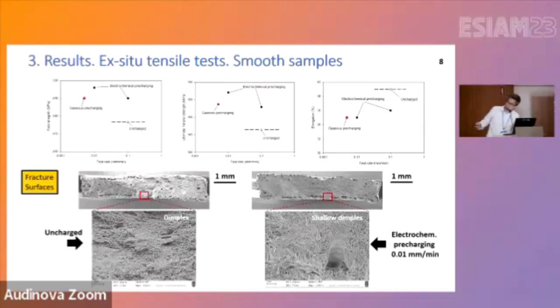Regarding the fracture surfaces, dimples indicating ductile fracture were observed in the uncharged specimens without hydrogen. However, in the case of the samples precharged electrochemically, which corresponds to this strain rate, this point, we have observed shallow dimples, which could be associated with hydrogen-enhanced local plasticity. This fact explains the loss of ductility.